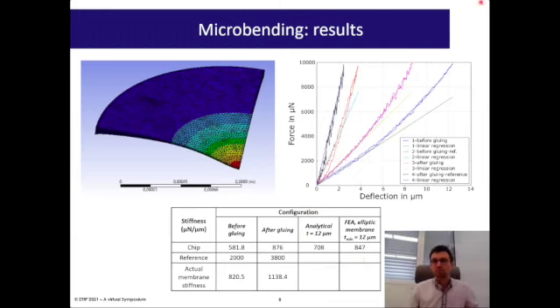The difference between the two experiments is not completely explained. It could be due to induced stress because of the gluing. The uncertainty on the real thickness of the membrane can also explain the difference between the experiments and the finite element analysis. Work is still in progress to better understand the effect of tip gluing, to extract both the elastic constant and the stress within the membranes.